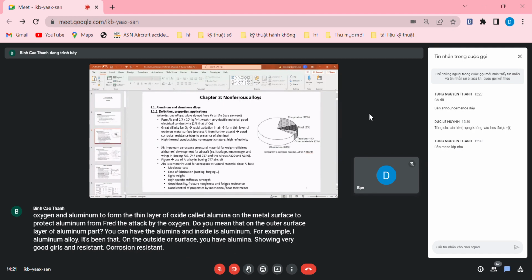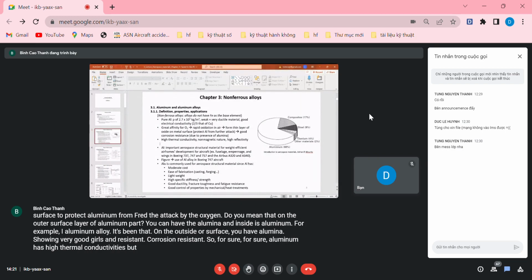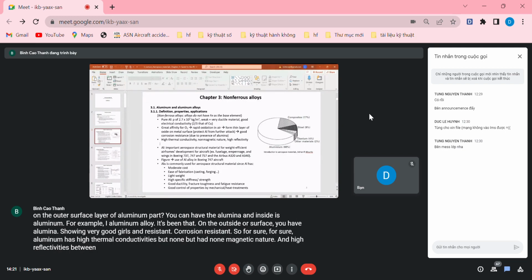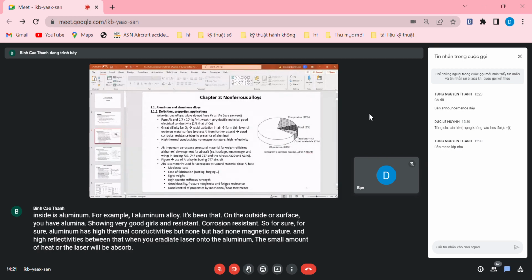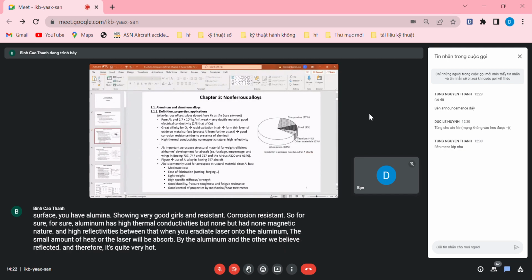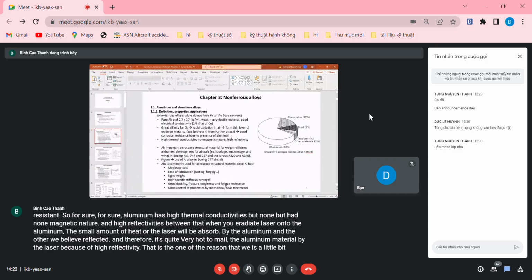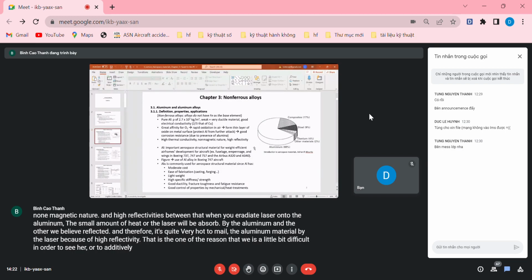Very good corrosion resistance. For sure, aluminum has high thermal conductivity, but also non-magnetic nature and high reflectivity, which means that when you irradiate a laser onto aluminum, a small amount of the laser energy is absorbed and the rest is reflected. Therefore it is quite hard to melt aluminum with a laser because of high reflectivity. That is one of the reasons it is a little bit difficult to sinter or additively manufacture aluminum alloys.